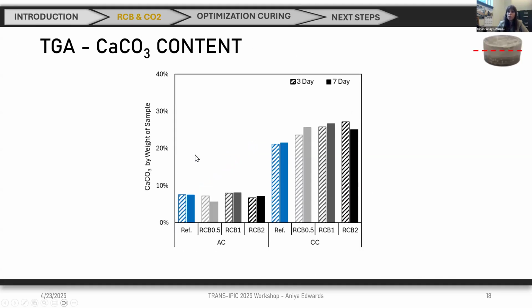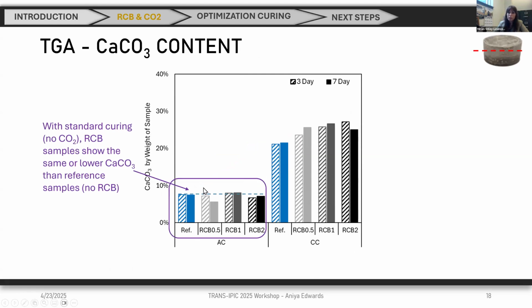Now, why is this happening? Well, there are many reasons, and I cannot go through all of them, but I just want to highlight one thing. This is the calcium carbonate of the samples at 3 and 7 days, and you will see that when we are talking about no CO2 curing, the amount of calcium carbonate is kind of the same for all of them, even lower for some of them with recovered carbon black. So there's not much of a difference from using carbon black when you have no CO2 curing in terms of calcium carbonate content. So we are not adding calcium carbonate content. That's what I want to say.